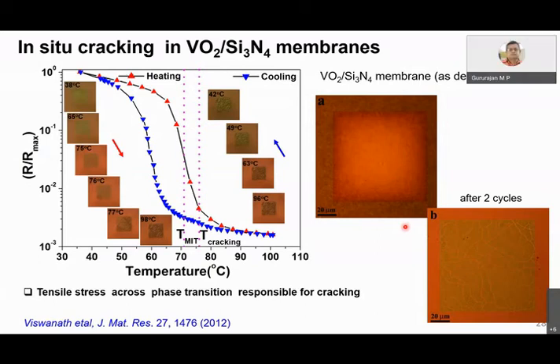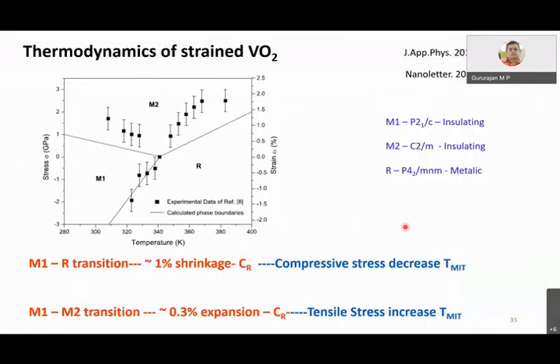It's almost like the BCT, in all the axes it is not uniformly contracting or expanding. In the C axis it is going one way, and the A and B axes the other way. But there is a clear volume change of, I would say, 0.3 to 0.5%. And you also see variants, because it is going from monoclinic to tetragonal as you increase the temperature. Correct. So the tetragonal variants should be such that they go back to monoclinic by symmetry if you add them up. Does that happen, or is it too complicated?